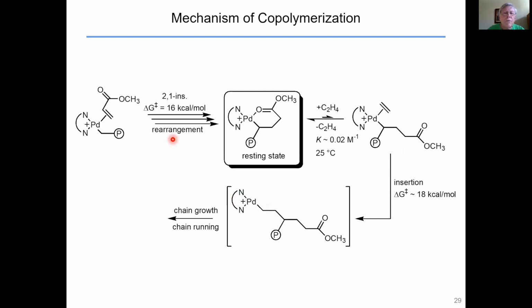So here's the overall picture. We're growing a chain. We bind methyl acrylate and it inserts in a 2-1 fashion. That barrier turns out to be lower than the ethylene insertion barrier, which is not surprising. It's kind of like a Michael addition. This is activated towards migration of the sort of anionic alkyl group, if you like. We generate the resting state, and then we have an equilibrium between the resting state and the ethylene complex that's going to then undergo migratory insertion with a barrier of about 18. We start growing a chain, and then as soon as it binds acrylate and inserts, we're back to the resting state.